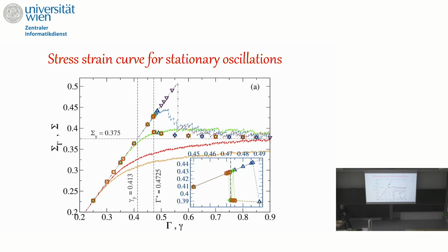Yes? These are the amplitudes of the stress and the strain. What does the instantaneous stress and strain look like? Because once you get above that yield point, I presume that you have an elastic response followed by yielding, followed by elastic, followed by yielding. How does that response change? Because this is the maximum value. Yes. What happens instantaneously is that you have, as you said, an elastic part, a yielding part, and then it continues like this. And does the yielding remain brittle, or does it become ductile, or does the yielding type change? No, it always remains fragile. Always you have the shear band.